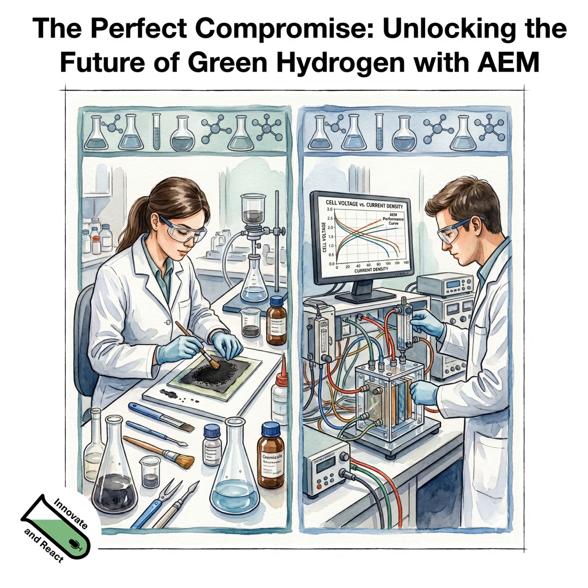This is also something we do: we compare the fresh material after our synthesis and the material after our long-term measurements to understand where the real active sites are. So it might change during the electrolysis process, and then you basically have a different material that generates itself in situ through the process.